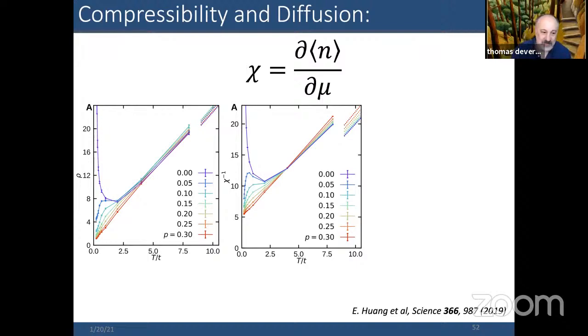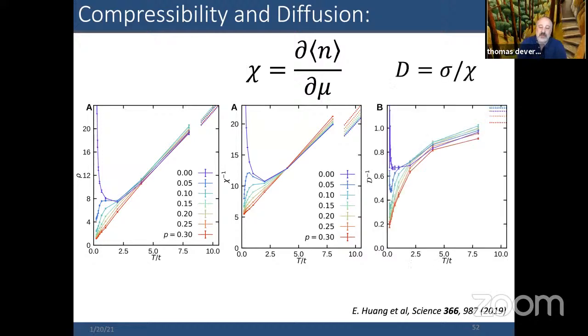So the resistivity going all the way down linear in temperature is dominated by chi, or one over chi, at least at higher temperatures, but at low temperatures, something else kicks in. And of course, by the Einstein relation, that is the diffusivity, or one of the diffusivities, which goes from being roughly constant at high temperature to something which goes linear with T, or at least strongly goes to zero as T approaches zero.